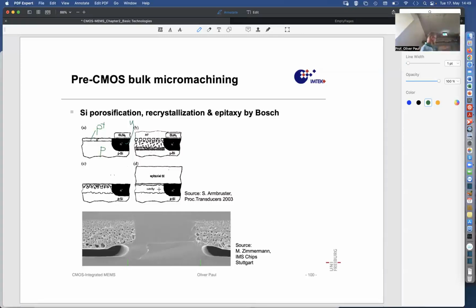And so at the end, you have an epitaxial silicon, and that silicon is monocrystalline, because making pores into silicon does not disturb the crystalline order of silicon. There is still the crystalline order of the silicon, and whatever grows on top takes over this order and combines into a dense layer, which is monocrystalline. It's a wonderful idea. Yes?